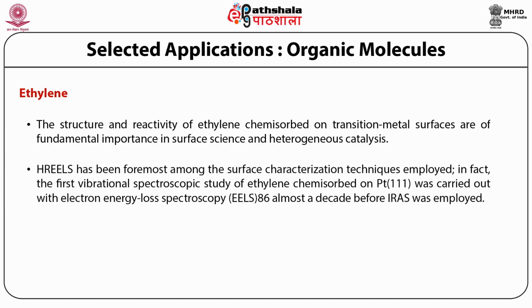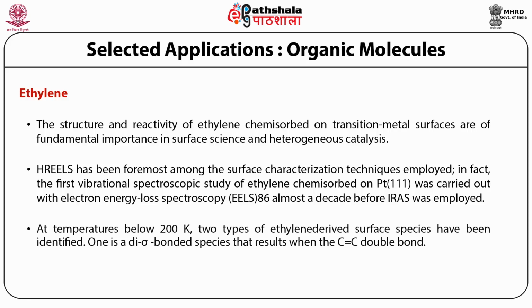HREELS has been foremost among the surface characterization techniques employed. In fact, the first vibrational spectroscopic study of ethylene chemisorbed on platinum was carried out with electron energy loss spectroscopy (EELS) almost a decade before IRAS was employed. At temperatures below 200 Kelvin, two types of ethylene-derived surface species have been identified. One is a di-sigma bonded species that results when the C=C double bond